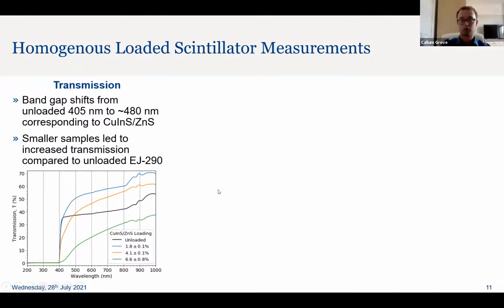So moving on to experiments on these loaded scintillators. First I'll talk you through the homogeneously loaded scintillators, and we have a transmission spectrum here. We have a band gap of the plastic at about 405, and then that tails off quite sharply for the unloaded spectrum, and you end up with a transmission plateau until about 800, where we have peaks and troughs corresponding to the polyvinyl toluene base absorbing.